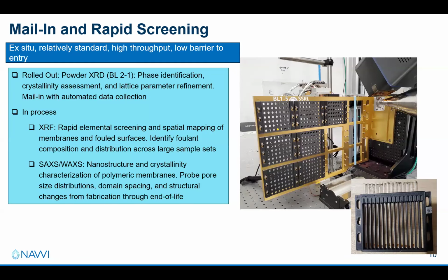This is an example of our setup at the SAXS/WAXS beamline where we can run, in this configuration, about 500 samples. Each one of those holes is a port where a sample goes. What we've been designing there are these holders that we can ship to people and they ship us back their samples. We do that for films and powders, and then we also do the same thing for capillaries. Those are designed in a way that the capillaries are secure in the little holder that we send. These were examples of just a film and water. For example, if you have a spiral-wound module, you cut it open, you can actually scan a lot of areas like that, so you get a full representation.